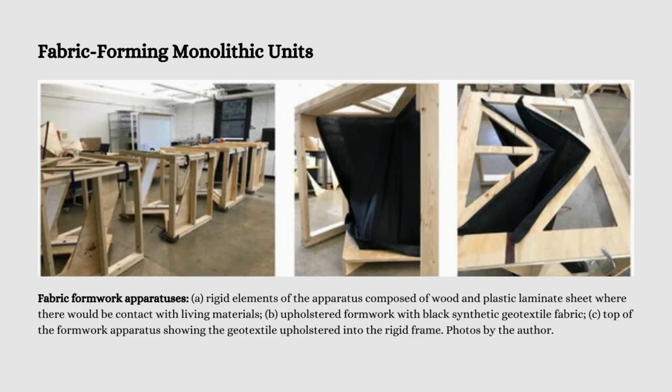The fabric that they chose to use here is a geotextile fabric that is synthetic. So in this case, the mycelium is contained inside the fabric and won't likely start to grow outside it, won't use that type of fabric as its food source, although sometimes it does. But in this case, that was one of the reasons for using this, to try to prevent it from growing into the fabric, because eventually you are using this as a mold. Eventually this will be taken out of that mold and will be free from the fabric.